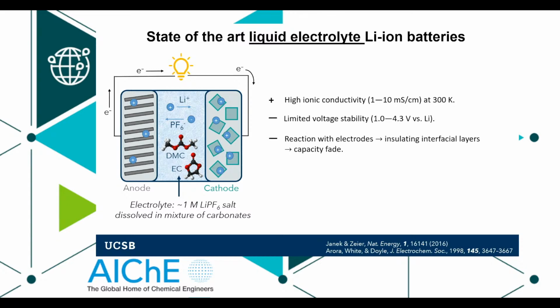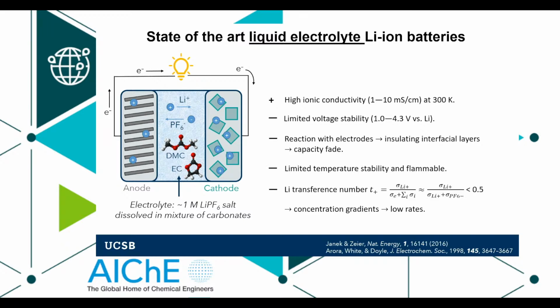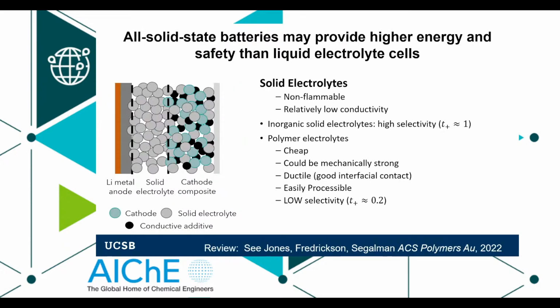And right now there's a lot of reaction with electrodes that create some capacity fade, which affects the long-term applicability of the batteries. And there's also some limited temperature stability and flammability. So for this reason, we're working a lot on trying to get the conductivities higher, also getting more of the conductivity to be carried by the lithium versus everything else in the system to get high rates. My group and many others have started working towards solid electrolytes, where they are inherently non-flammable, but have relatively low conductivity. And that creates a challenge of how can we make these better so that the overall device works better and could also be cheaper and more mechanically strong.